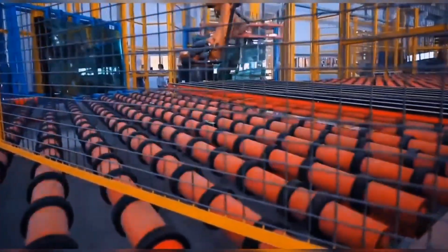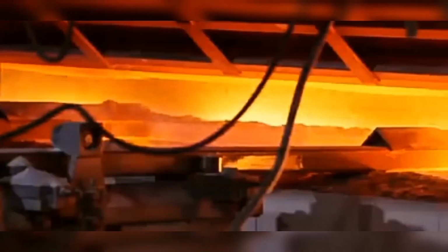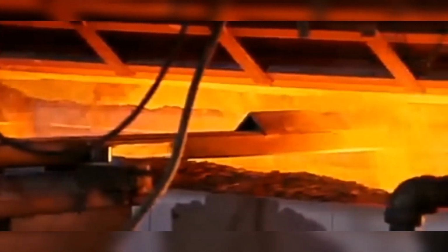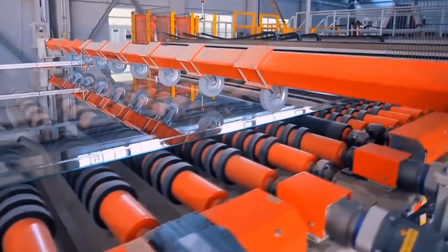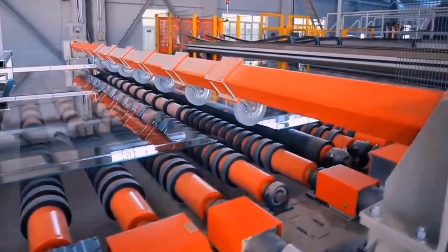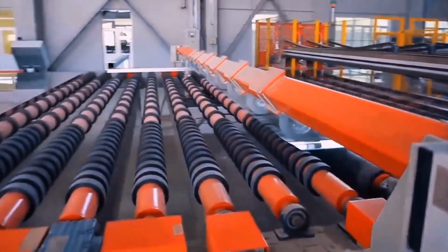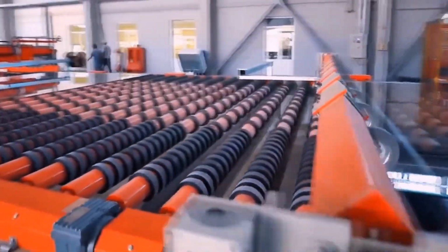Thermal profile and transfer to the cold end. While in the bath, the glass is held at very high temperatures on the hot end, at approximately 1100 degrees C while entering the bath, and gradually cooled. It is usually reduced to approximately 600 degrees C at the point where it is lifted off the tin onto rollers. From there, it enters the annealing lehr. Cooling rate across the tin bath and transfer to rollers must be controlled to avoid distortion and internal stress.